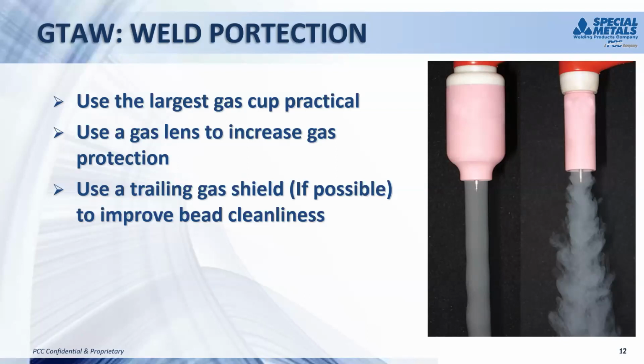A lot of times you'll see people adjusting their tungsten well beyond the gas cup, and that causes a lot of problems because the further you stick that tungsten out, the less shielding you're going to actually get to protect the tungsten and that weld. If possible on a mechanized process, shielding trailing gases are always recommended because that just gives you a little extra shielding to let that weld cool a little more and reduce the amount of oxides that could be on there. Next slide.